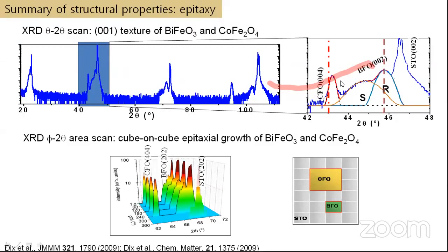On the bismuth ferrite part, you have two peaks. One is called strained, and the other one is the relaxed one. Apart from that, this is pure, so you have an epitaxial film. If you have a phi scan, you can clearly see that your bismuth ferrite and cobalt ferrite go cube on cube. So it is growing epitaxially, and there is no confusion on this one.